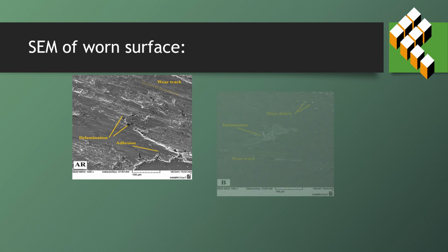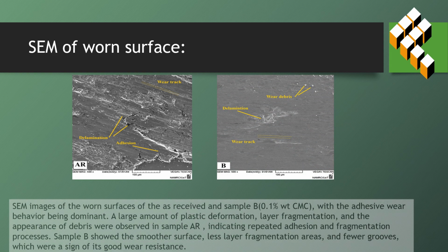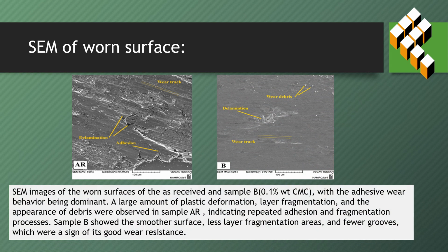SEM of the worn surface. As shown in the two figures, SEM images of the worn surfaces of the as received sample and sample B with 0.1% weight CMC, with the adhesive wear behavior being dominant.